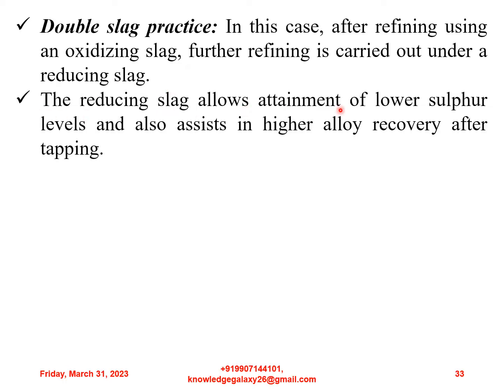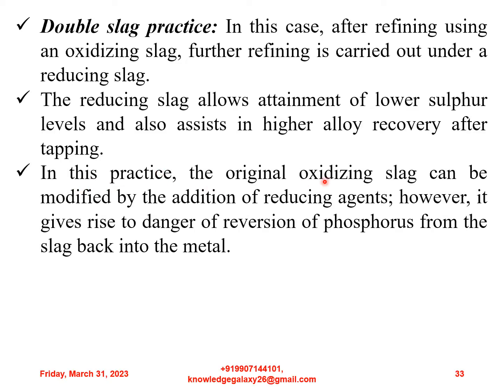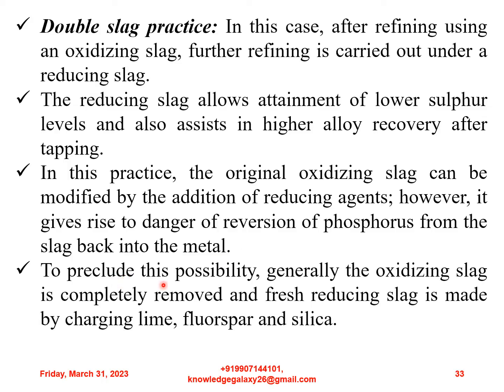The reducing slag allows attainment of lower sulfur levels and also assists in higher alloy recovery after tapping. In this practice, the original oxidizing slag can be modified by the addition of reducing agents. However, it gives rise to danger of reversion of phosphorus from the slag back to metal. To preclude this possibility, generally the oxidizing slag is completely removed and fresh reducing slag is made by charging lime, fluorspar and silica.